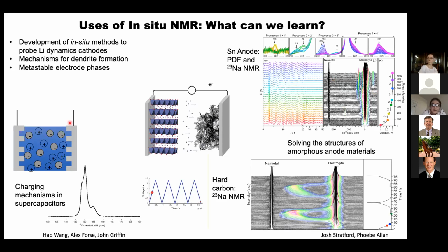And just to give you another flavor of where else we can use these types of methodologies, this is actually a supercapacitor. Supercapacitors are again carbons, but now instead of these hard carbons, where you've got a very dense carbon, you activate your carbon to give you a lot of internal porosity. These carbons have internal porosities of maybe even 1600 meters squared per gram. And so they're almost graphene sheets held apart to let the ions in.